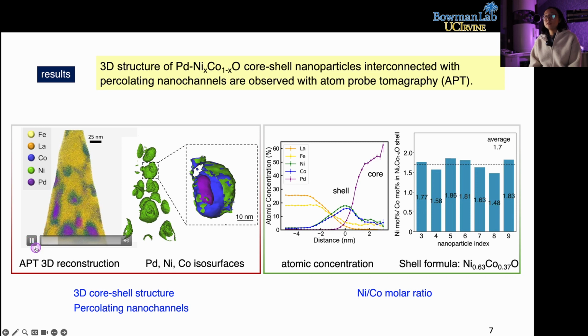We can see from this animation, the exsolved nanoparticles are distributed well in the whole thin film, and they are connected by the percolating channels between them. We can also see the nickel, cobalt, palladium isosurfaces to check their 3D structure. Using atom probe tomography, we surveyed several nanoparticles, and we found the shell formula of this nickel cobalt oxide is nickel 0.63, cobalt 0.37, oxygen. So nickel takes up the higher concentration in the shell formula.